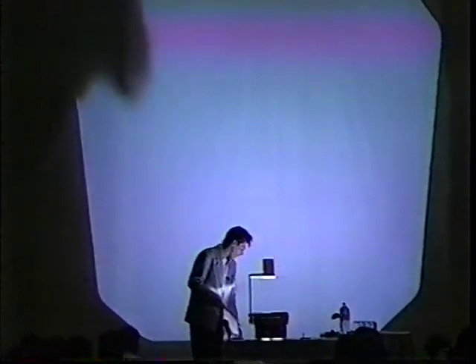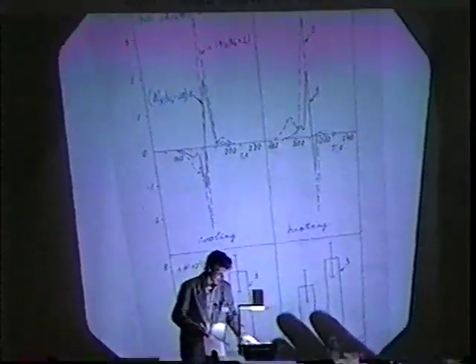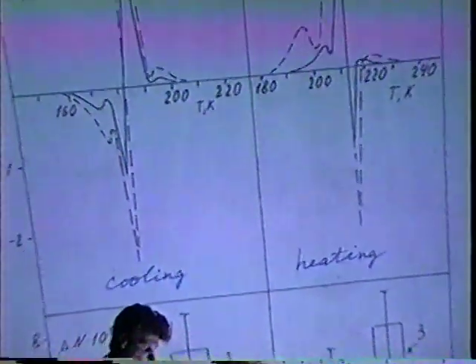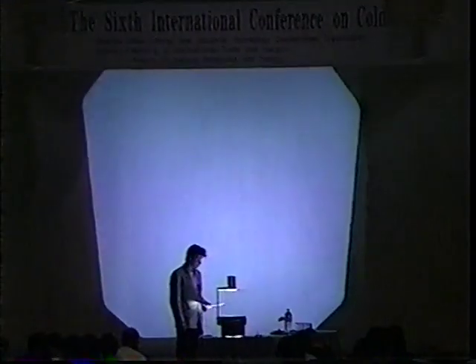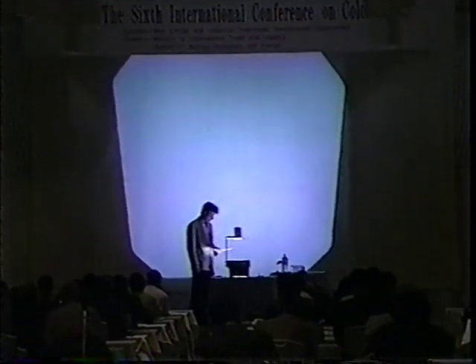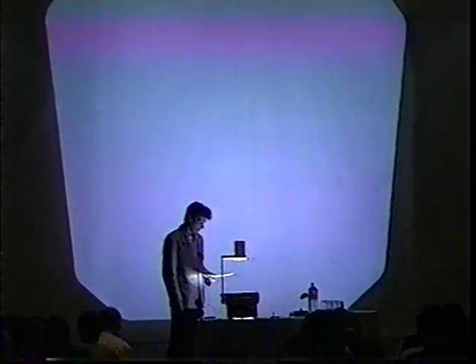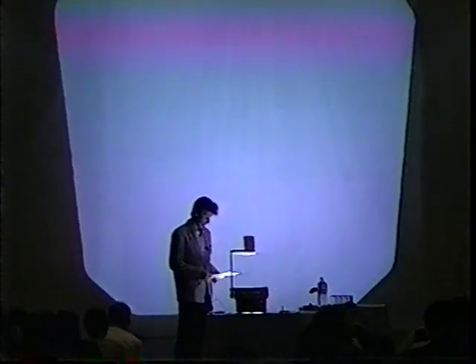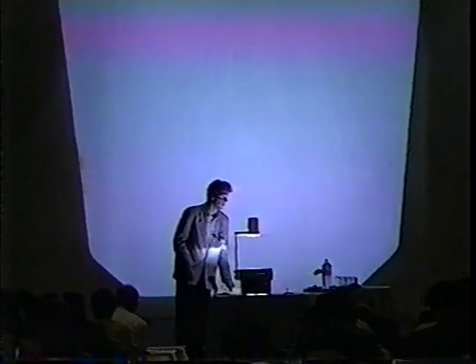For high deuteration degree, the sign of neutron emission is positive. For deuteration degree 80%, the sign of emission in the high neutron background is negative. Simultaneously, in DKDP crystals, the suppression of spontaneous deformation defects and transformation is observed. In the present work, we will demonstrate that the absolute value of neutron emission and its sign, positive or negative, is dependent upon external thermal neutron flux, crystal mass, and its deuteration degree. Thank you.